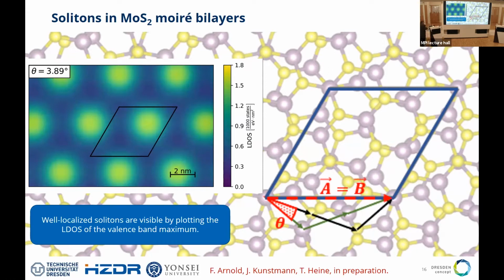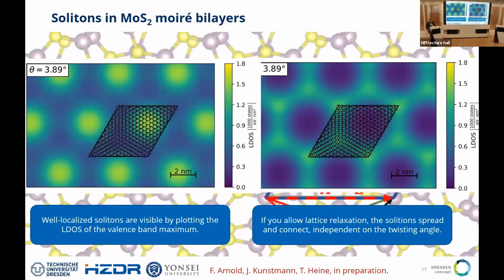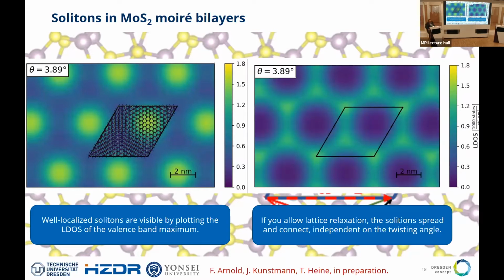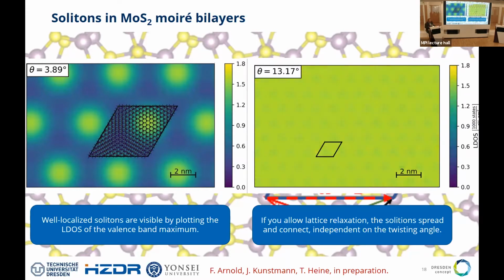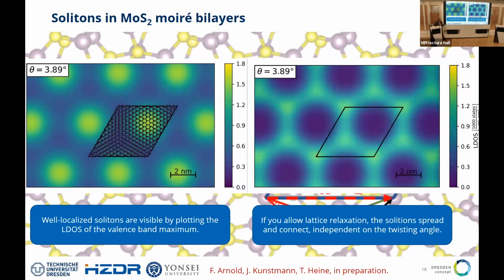What happens if you include that in the simulation, if you include that in the calculation? So here you see the structure at this 4 degree, and your solitons are transformed to a honeycomb superlattice. Okay, so you don't have the soliton any longer. You have now something like a superlattice, and it stays like that. Right? It stays like that, and you will never have this very nice pure soliton regime. So what can you get now in experiment? That's something to be discussed. I mean, of course, if you think about encapsulation, maybe you end up on that side. If you have a freestanding material, maybe on graphene or something like that, you're more on that side, and maybe you can actually flip from one to the other.